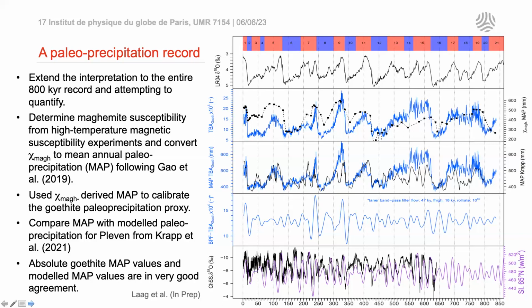So in this study, for all of the lower Danube, precipitation was modeled through time. And when you take the data for the spot that was for Pleven, it's the black line, and you can't really deny that there's a very nice fit between the modeled precipitation data and ours, even if you don't look at the numbers of the quantification, just the amplitude trends are very good. And it happens that also the numbers, because they're on exactly the same scale, seem to match.